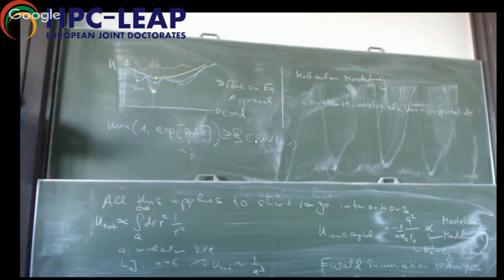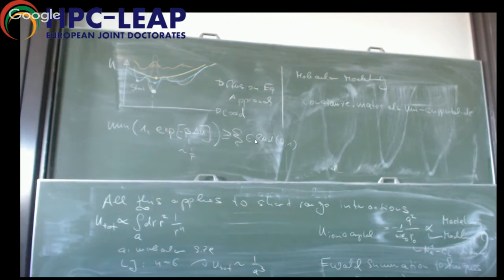So it's basically two types of diffusive processes intermingled, and you can handle this as well with the appropriate Green-Kubo relation. And there are Green-Kubo relations for electrical current conductivity and other transport coefficients as well. And I would actually most of the time suggest these methods for transport coefficients, and that can be done in equilibrium.